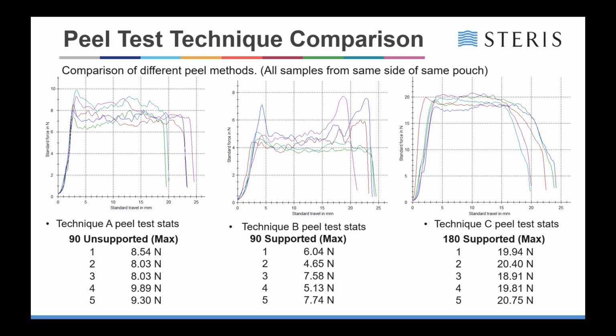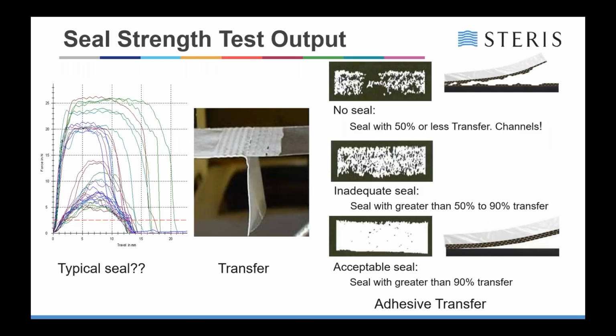And also, if you're looking at different lengths or sizes of pouches, the graph on the left-hand side is from a series of pouches that were approximately 2.5 meters long. The bottom graphs were from a part near the closing seal. The middle ones were from the end of the pouch, the chevron end, and the top ones were the center of the pouch, again showing the different seal levels across the different pouches.